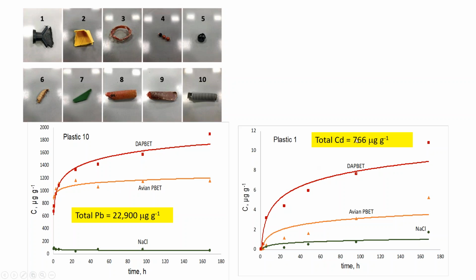This is plastic 1. You see total cadmium here was 766 micrograms per gram, and we get about 8 or 9. So we get about 1% here out of this plastic, which has been recycled from electronic waste. No surprise, because it's a black object.